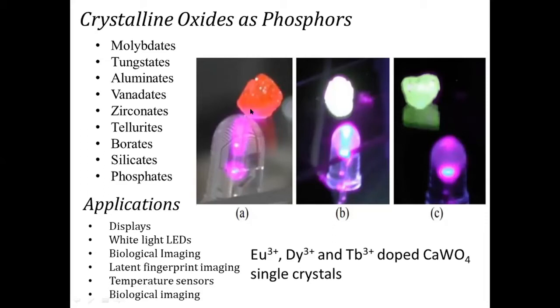And here you can see an LED made out of a phosphor. Here also there is an LED, but that LED emits UV light, 250 nanometers or 300 nanometers, light which you cannot see. But inside this LED, there is a crystal of phosphor. That phosphor material absorbs UV light and emits red light, or it can emit white light also. And it can also emit green light if it has terbium.